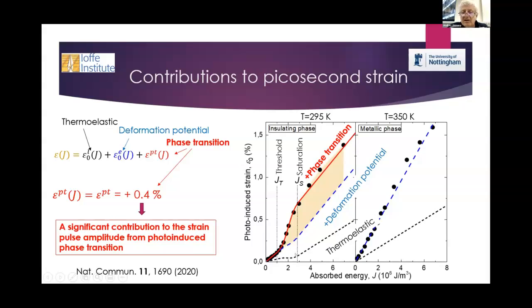Then in this region, it is a bit more complicated because we need to take into account that the energy actually is absorbed, but all energy doesn't go to heating. It goes to phase transition. So there is actually no heating anymore, and then again the heating starts.